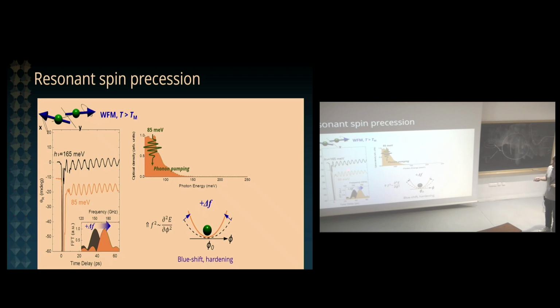For some magic, now the lifetime of the magnon mode becomes much longer. I still personally don't understand this phenomenon, and I haven't seen this addressed properly anywhere. But for some magic, magnons in the high temperature non-collinear state become much longer lived, which is convenient for experiments. And here I'm contrasting again what happens when you are off resonant and when you are resonant. You see that this time we again have a change in the frequency, but this time we are hardening the potential. It's becoming faster.